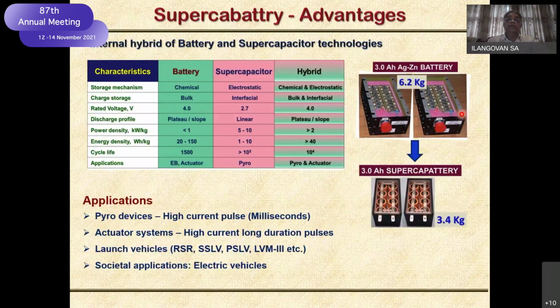So we could increase the capacity, not the capacity, the energy and power wise. If you look at it, see here the battery was able to give only 1, but the supercapacitor was 5 to 10, but the hybrid is able to give nearly about 3, much more than 2 we were able to get. Without compromise on the energy density, see, 20 to 150, we are able to increase it to nearly 40 level. So with the combination of these two, we are able to reduce the battery weight by half. So that gives a tremendous scope for us to improve.